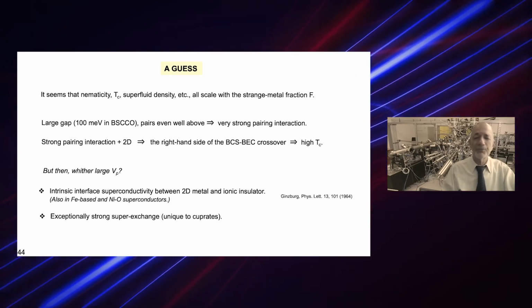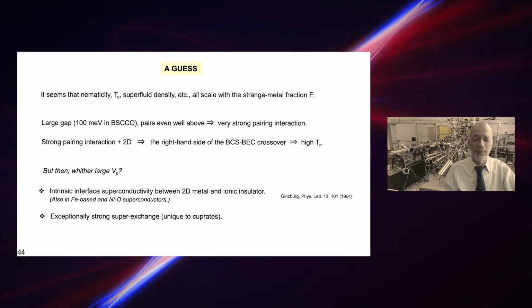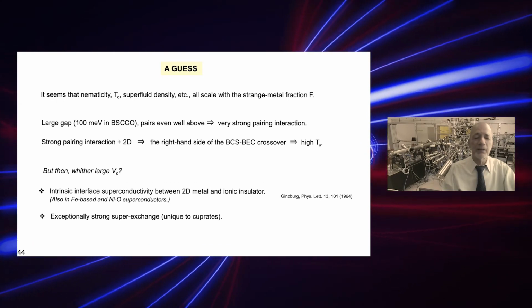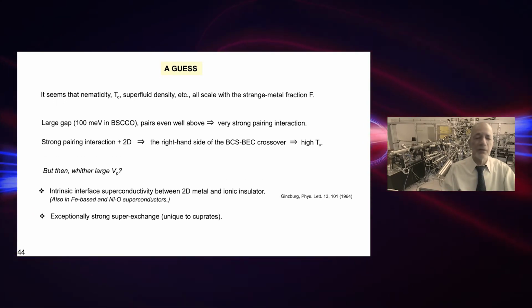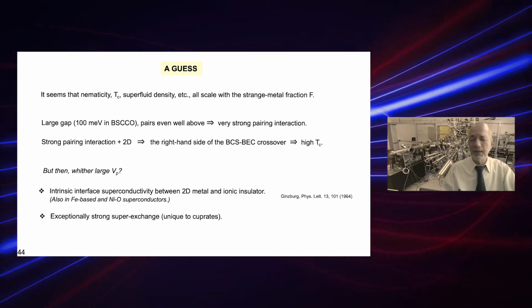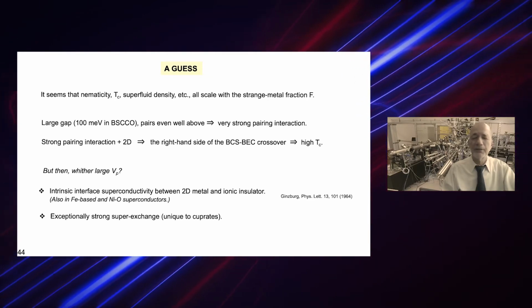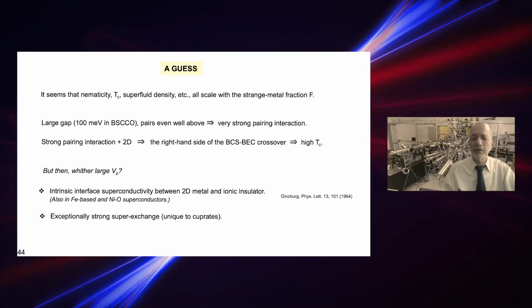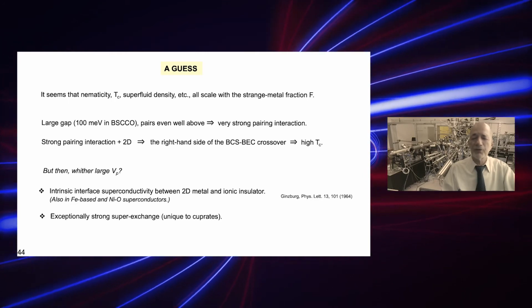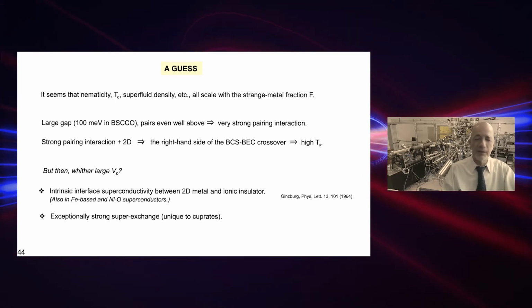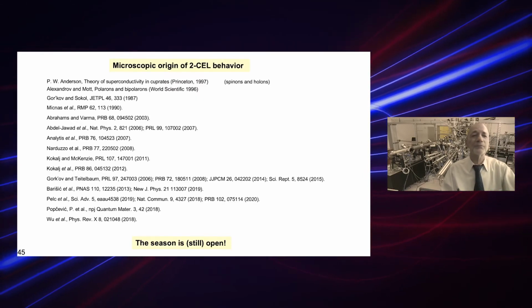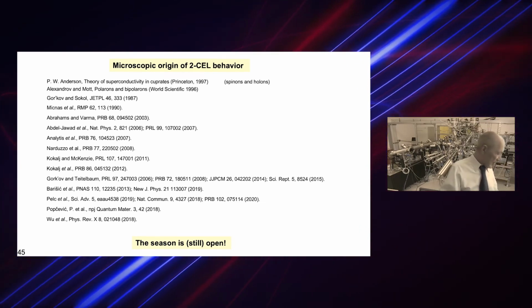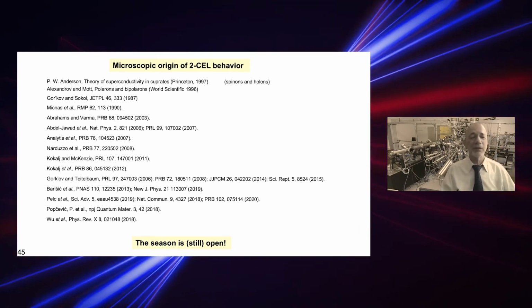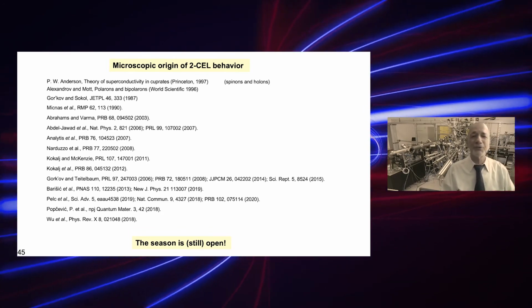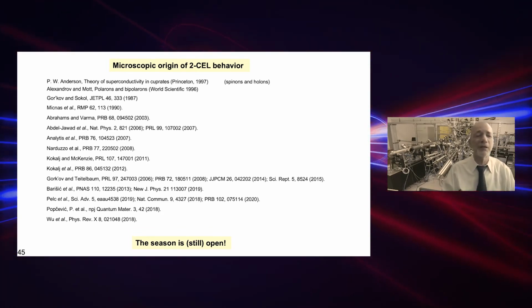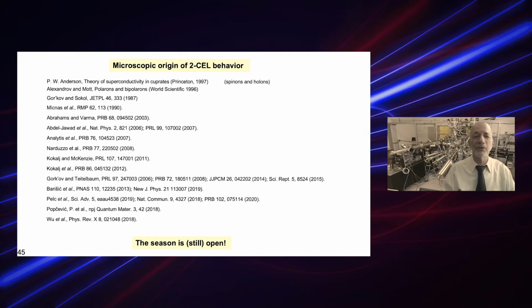The second thing, which is probably unique to cuprates, is that the superexchange is exceptionally strong, and this comes from the degeneracy between the copper 3d and oxygen 2p orbitals, which is not true for any other oxide. Now, this was my guess. For more serious attempts, you can look at any or all of these